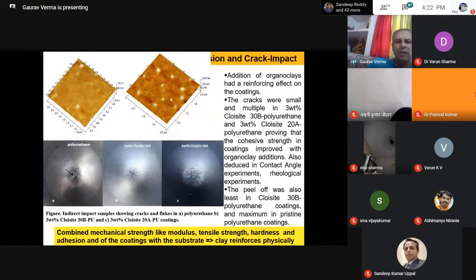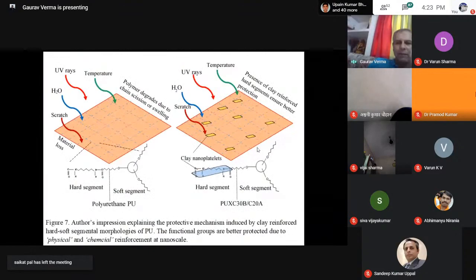And how I show that is in terms of creating an AFM image of a pristine coating which you see on your left hand side, and on the right hand side you see a nanocomposite coating. I would be able to better explain how this nanocomposite coating behaves better under impact conditions, because what happens under an impact, the portion of coating which comes off the substrate is much higher for a pristine coating as compared to a nanocomposite coating. And let me explain it with this simple drawing I've made, wherein this crisscross formation is actually the polymeric chains, and because we are dealing with a cross-linked polymer, and how it can be better protected when you introduce these nanoplatelets.